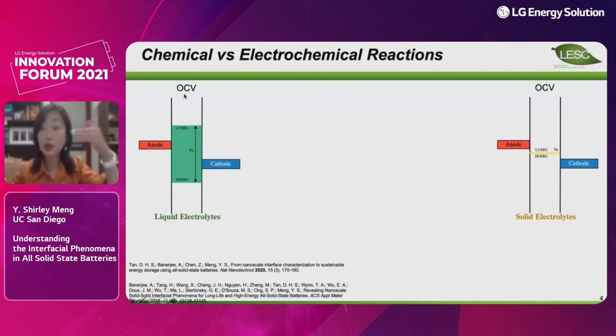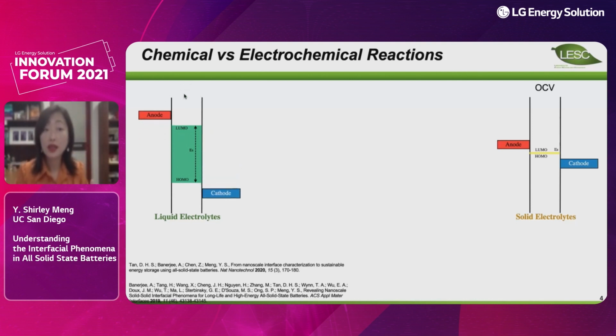The anode and the cathode are stable when you just assemble the battery. When you start to sweep the voltage, then the formation of the interfaces is very important. That's the working mechanism in liquid electrolytes, and our pioneer scientists have studied this a lot. I think today's earlier talk by Professor Jeff Dahn shows there's still a lot of room to be improved when we change the interface stabilities of the graphite and NMC cathode.